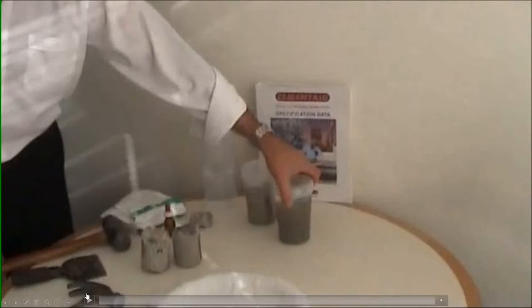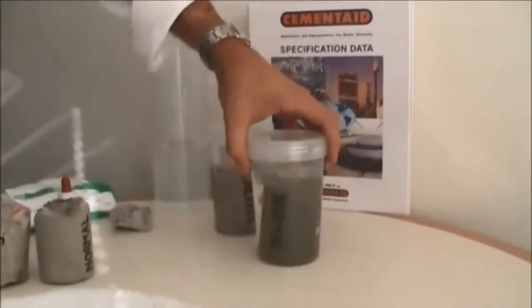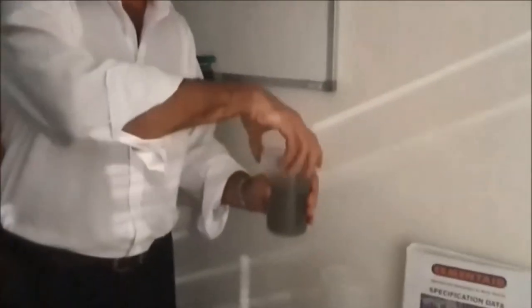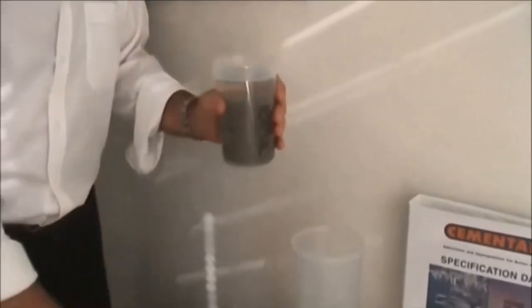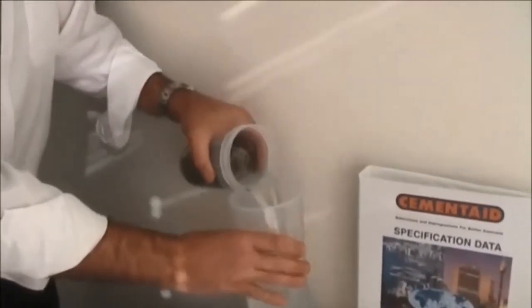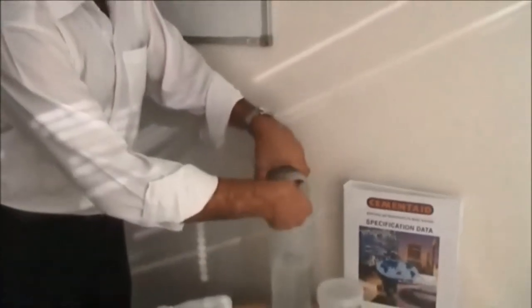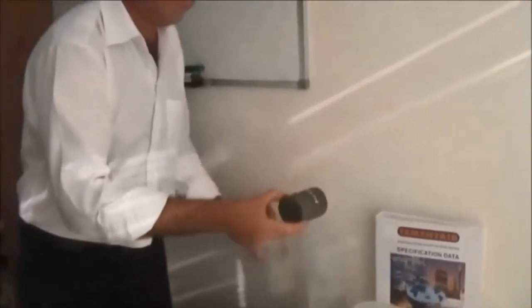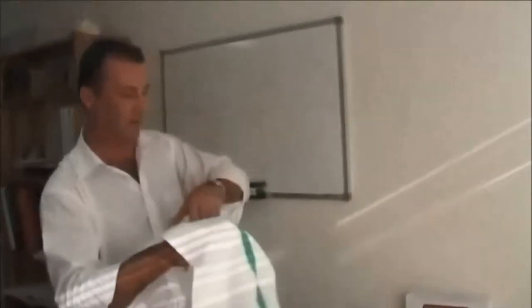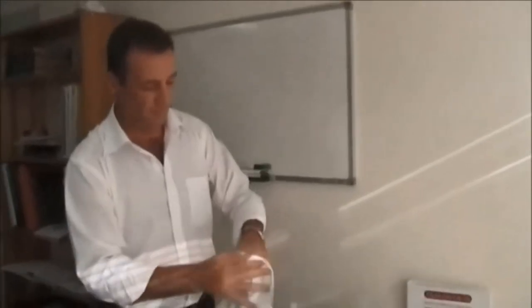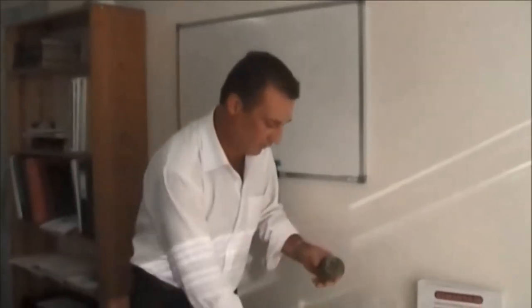So the samples here, I'll run the little video now. They've been in that water chamber there for 7 days. Now, bear in mind, this is concrete which had a water absorption of less than 1%, and they were put into these containers and left in there for 7 days. My colleague there was just showing that the water level had actually dropped in the container, so that water's gone somewhere. This is an example of an integral waterproofer which performed very, very well in the laboratory when tested in accordance with that British standard. But it's a very simple test now, just to break that sample open and see what has happened after 7 days.